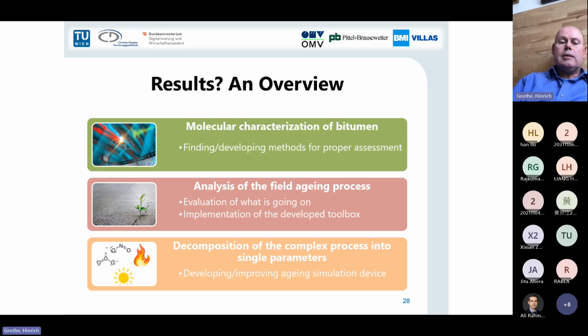So the result we are longing for is the molecular characterization of the bitumen, finding and developing methods for proper assessment, and the analysis of field aging processes. So evaluation of what is really going on with our material on the road. And we, of course, want to apply a kind of chemomechanical toolbox. So that means we also want then to correlate our chemical findings, that means our spectroscopy, with microscopy and with rheology. And finally, we want to break that problem down and develop and improve aging simulation devices.